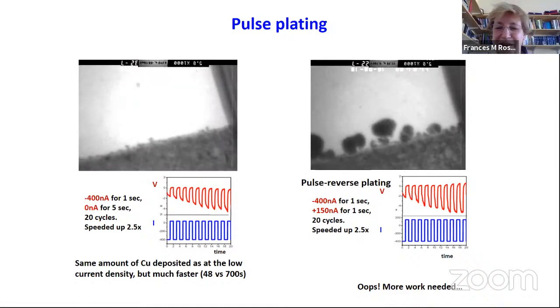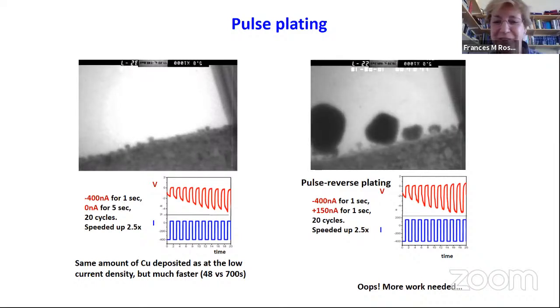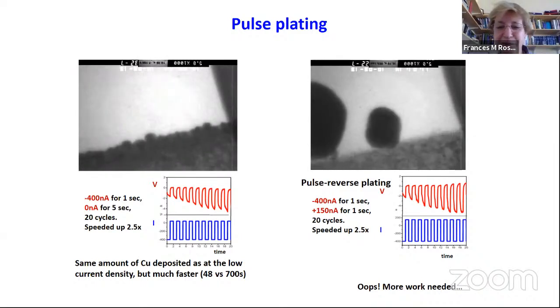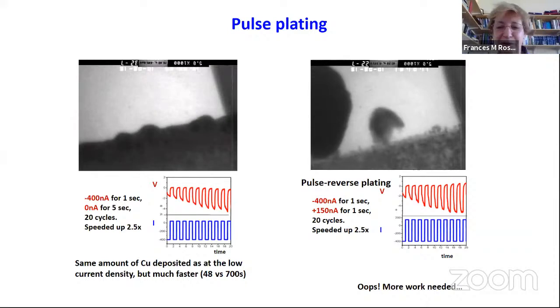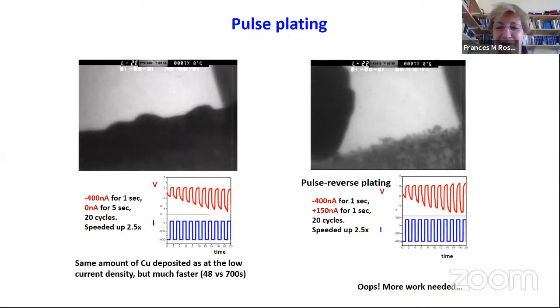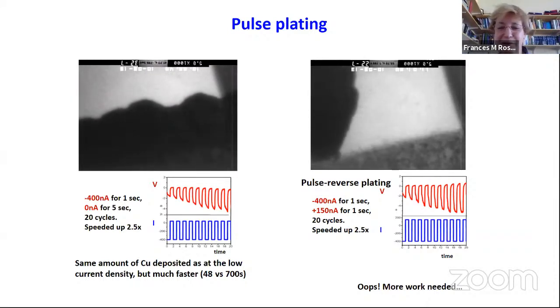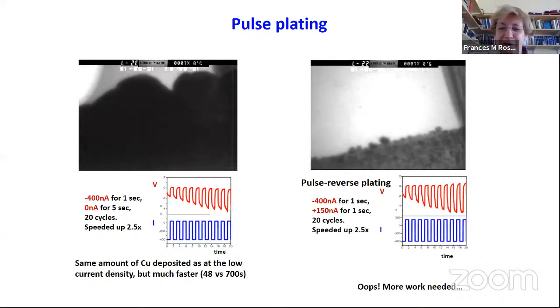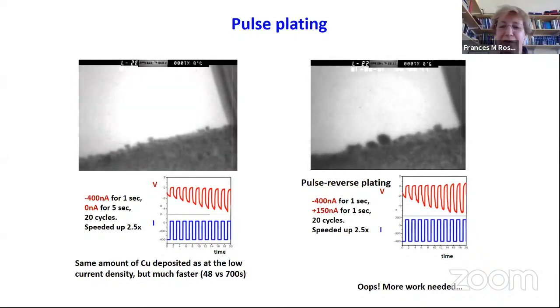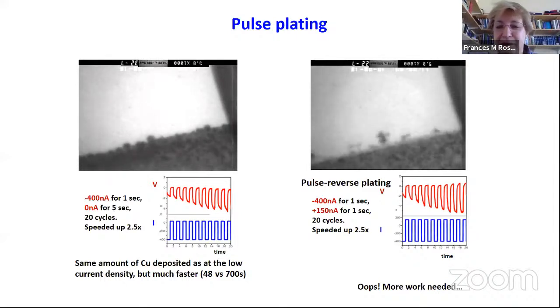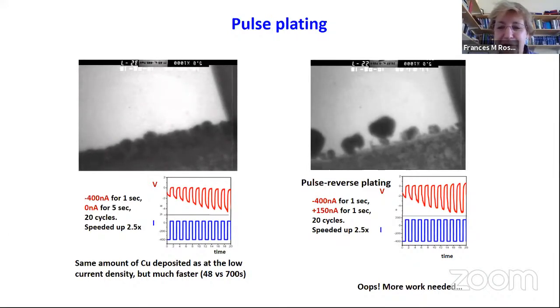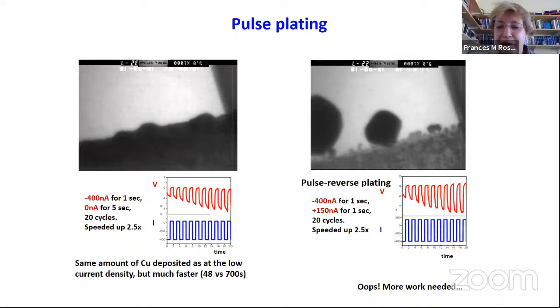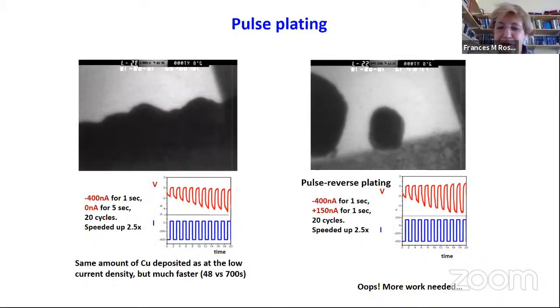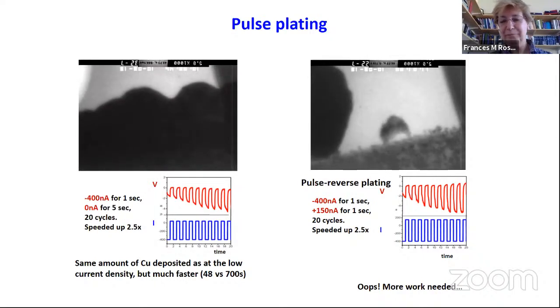But instead of making it smooth, this actually seems to lead to a coarsening effect. So this is one of my favorite movies. I don't know scientifically how much we can learn from this, but just visually to show that this sort of inequality gets exacerbated during growth, because the larger object is just stealing all of the material that's being released by the smaller ones when you do the etching.